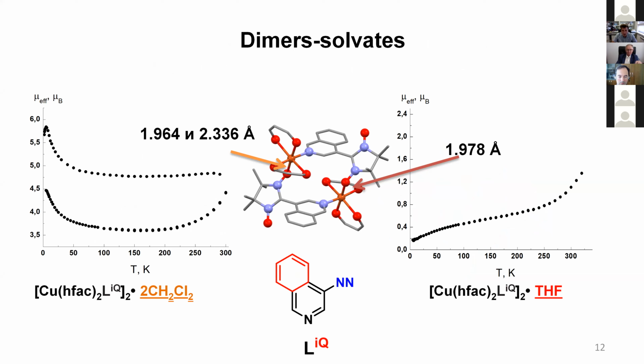crystallographically independent. In one of them, the copper-oxygen nitroxide distance is 2.3, and in the other 1.9. So for the first molecule, we can assume the presence of weak ferromagnetic interactions in exchange clusters, and for the second, a strong anti-ferromagnetic one. In the tetrahydrofuran solvate, the short copper-nitroxide distance is already present at room temperature, and the magnetic behavior suggests strong anti-ferromagnetic interaction between paramagnetic centers.